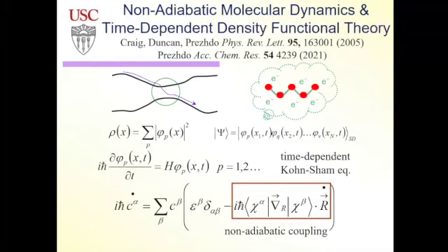What we do, we model excited state dynamics. You shine light on some material, lots of energy is put in. You want to see what happens with this energy, and you want to steer this energy to productive processes like solar cell or photochemistry and avoid energy losses to heat, for example. To do this, we developed a methodology which combines real-time TDDFT, where we describe electrons quantum mechanically, and the vibrational motions are described classically.